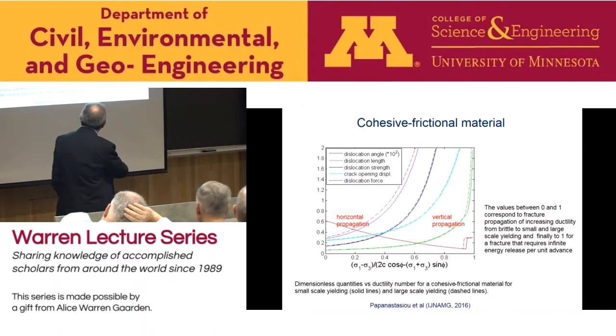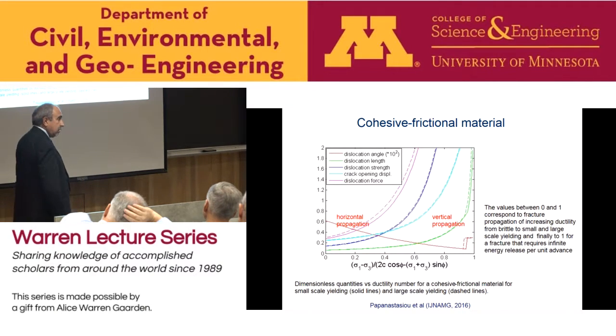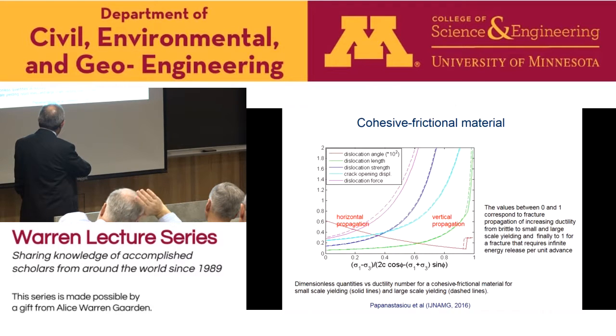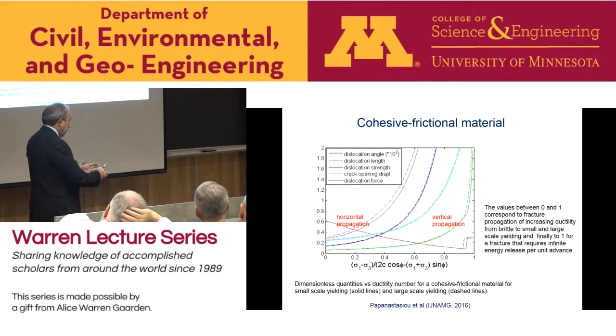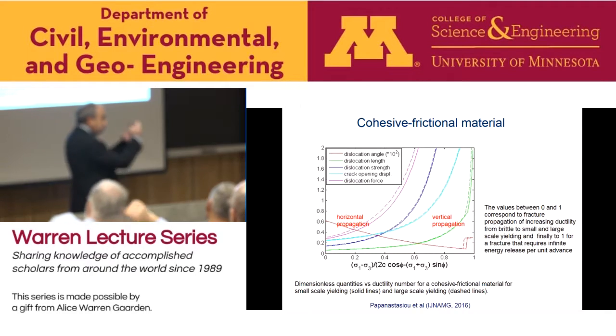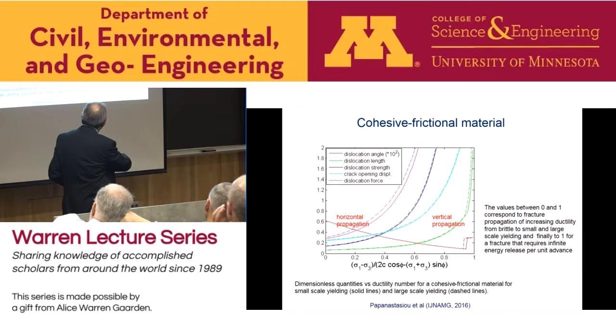Similar results when we have a cohesive frictional material. Now the critical parameter is this one here, okay? Because I will use this parameter as the brittleness index later. Again, isotropic will be close to this area. And this more likely corresponds to the case where we propagate the fracture horizontally. It's not exactly on the zero line. It's not fully isotropic, the stress field, because we have the third stress as well. So we are around this area, let's say. And then we go to an anisotropic stress field to propagate vertically. Again, we are in this area, so we need more energy to propagate the fractures, to create vertical fractures.